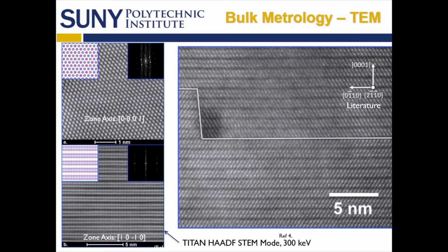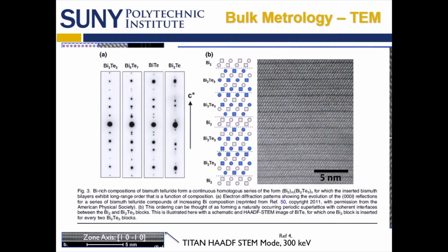It turns out these things are used for other purposes other than topological insulators, and the literature does have a lot of information about defects, as you see this crystal defect there. It also has information about bismuth bilayers between bismuth telluride, which is a sister material or brother material, whatever you want to say, to bismuth selenide.